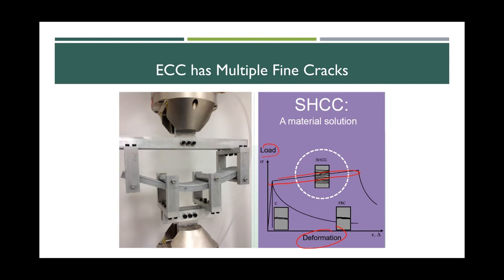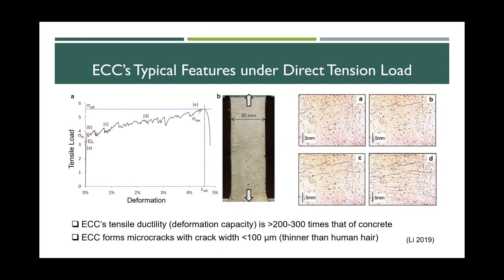So with that, we have the typical ECC features in direct tension. First of all, this is a sample with the direct tension at both sides. And you see that the deformation can go to 5%, compared to normal concrete at 0.01 to 0.02%. So the tensile ductility, or what we call the deformation capacity, goes to 300 times that of normal concrete. And throughout this deformation, we formed microcracks with crack width less than 100 microns.